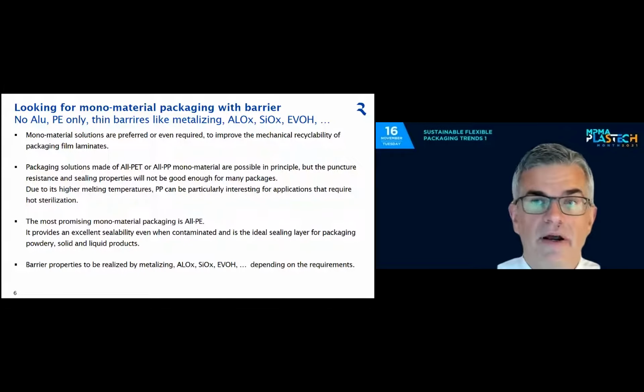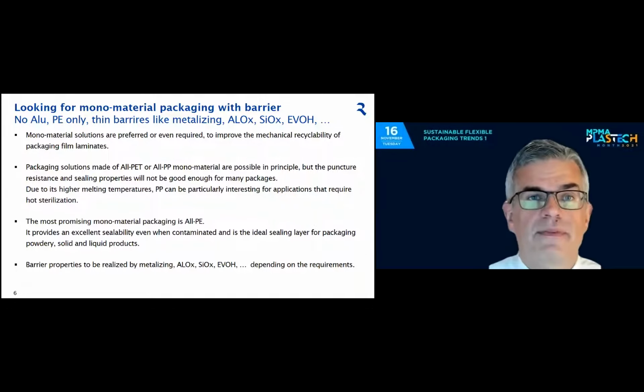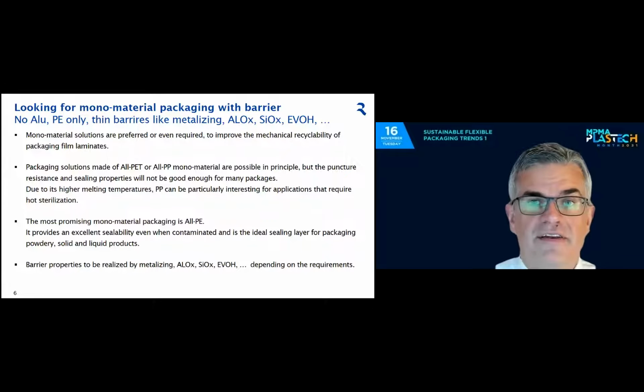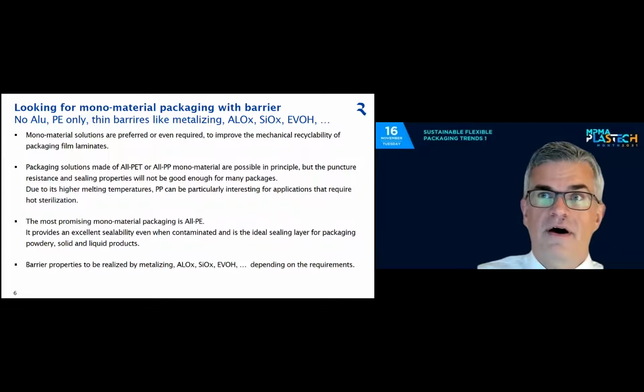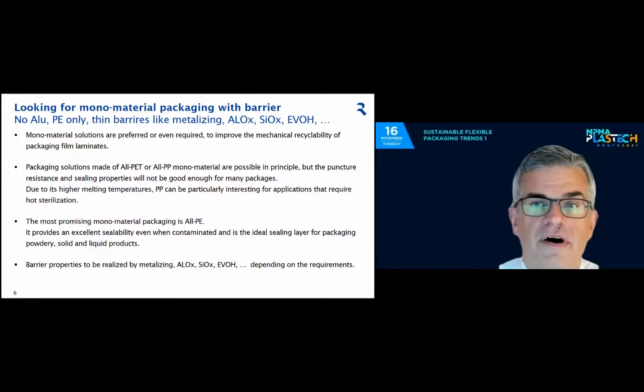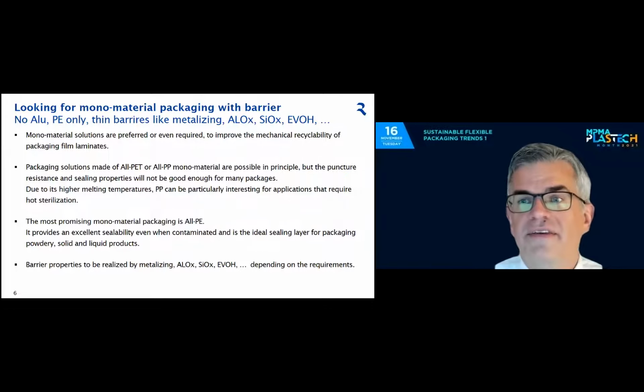So if you look for a monomaterial packaging with a barrier, this means avoid the aluminum, use polyethylene mainly, and create barriers like by metallizing, by ALOX or SiOx technology, or by a very low content of EVOH, wherein one usually says that the content of EVOH should be less than 5% in total in order to name it being recyclable. So the EVOH layer in such pouches shall be very thin. Solutions of all PET or all polypropylene monomaterial are possible in principle, but the challenge here is meeting the puncture resistance and the sealing properties for lots of kinds of packages. So a solution based on PE is favorable.